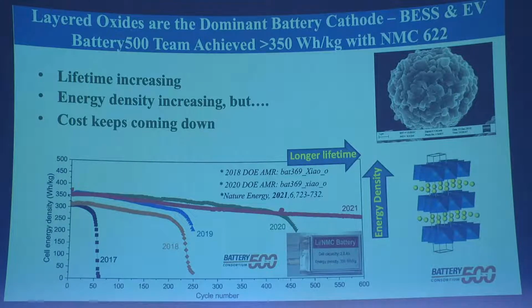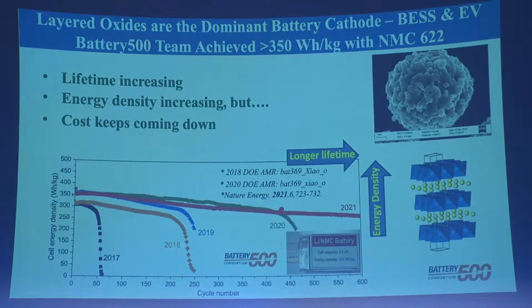I said this project's been going on now. We finished our first 5 years last September. If you look at the plot here, the data on the left-hand side is 2017. You can see we got 50 cycles out of this material at 300 watt-hours per kilogram. Then we went up to 250 cycles a year later. The following year, we increased the energy density to 350 and got the same number of cycles. And today we're, I'm told, close to 1,000 cycles at 350.